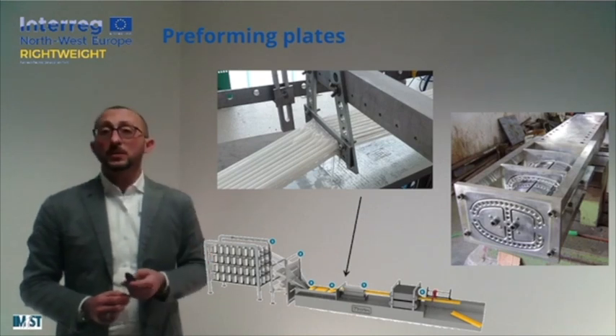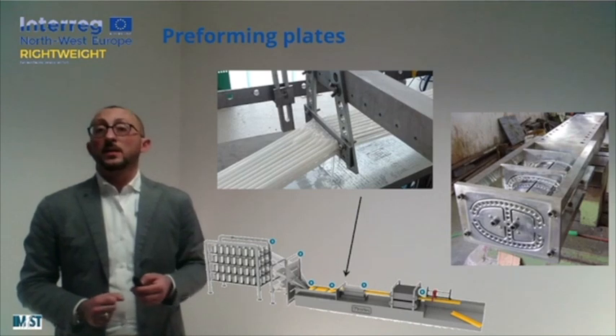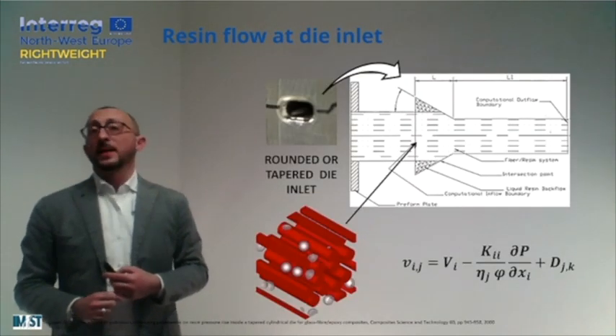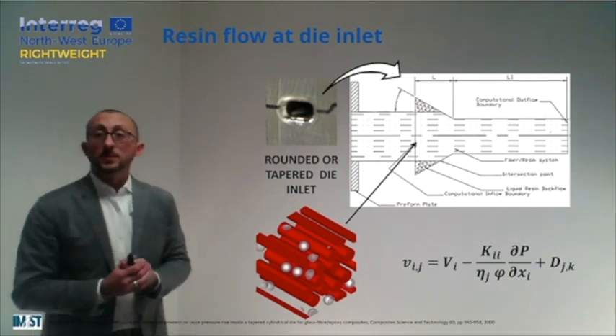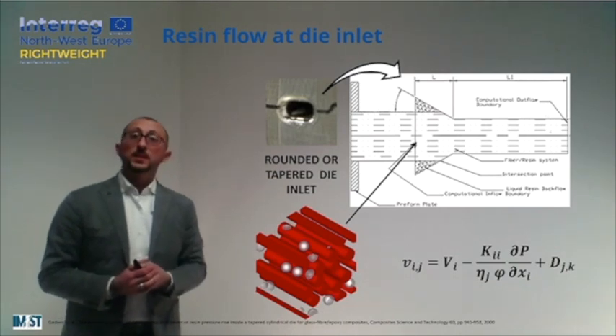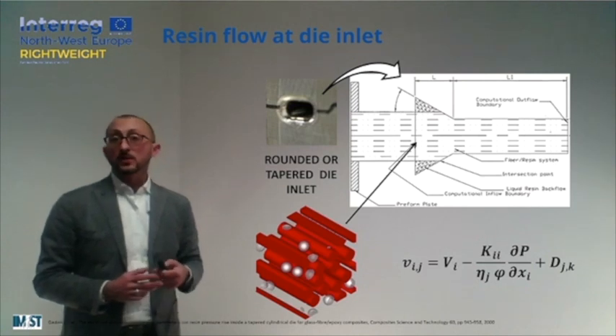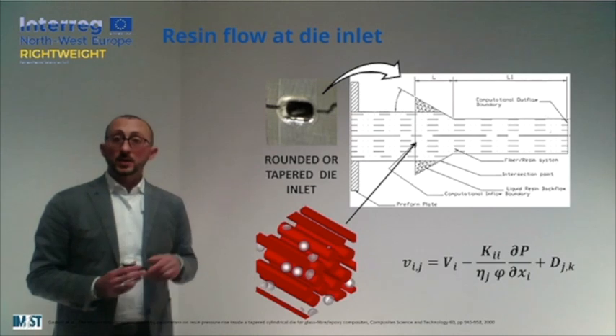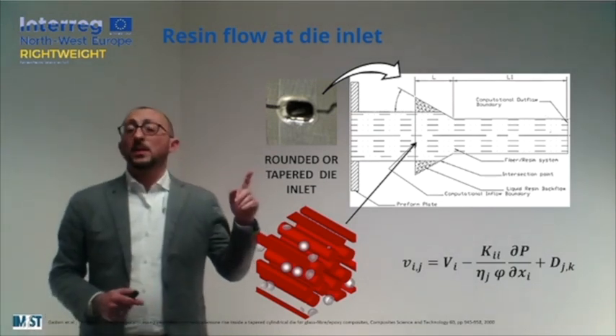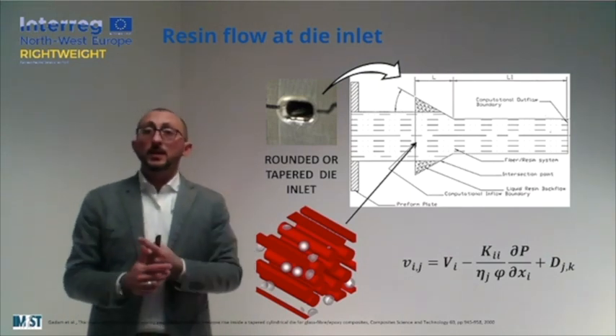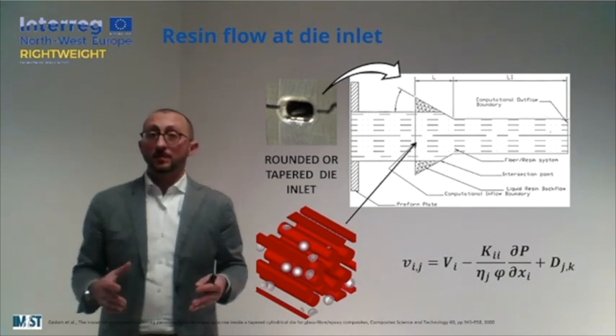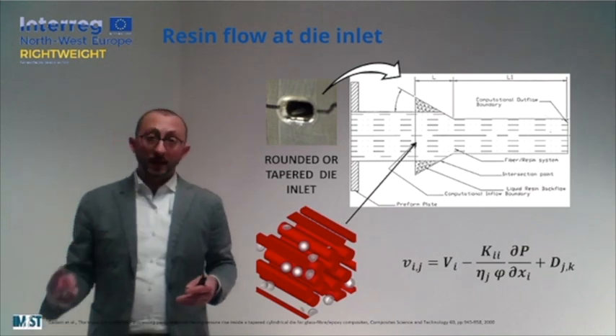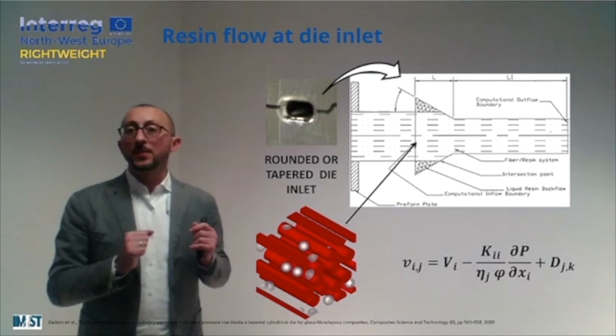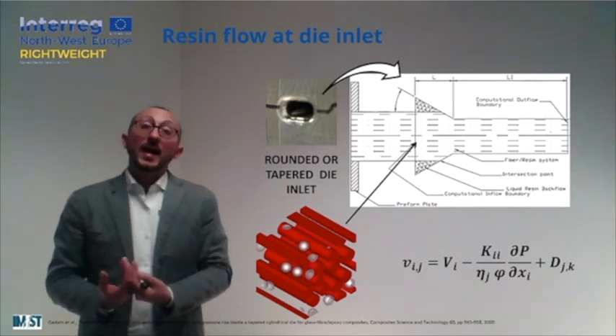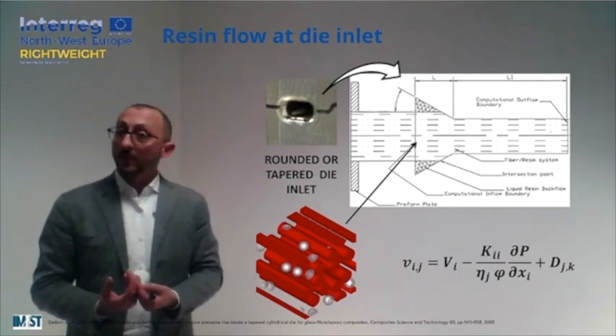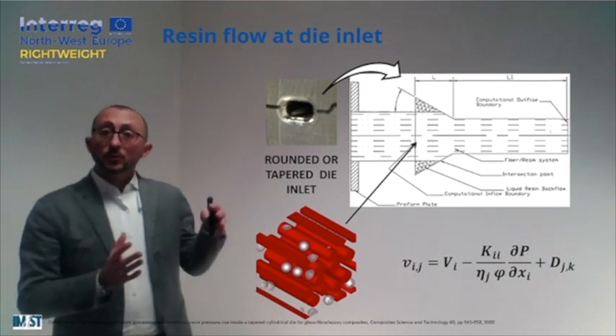The impregnated tows are now ready to go inside the heating and curing die, and this die, that is actually the device that is providing the shape and is curing the material that we are processing, is typically realized using a rounded or tapered inlet. This particular shape that you can see here is used for two basic reasons. The first one is to avoid any damage to our fibers. And the second one is that using this kind of shape, we can naturally achieve an increase of the liquid pressure of our resin due to this kind of compaction.